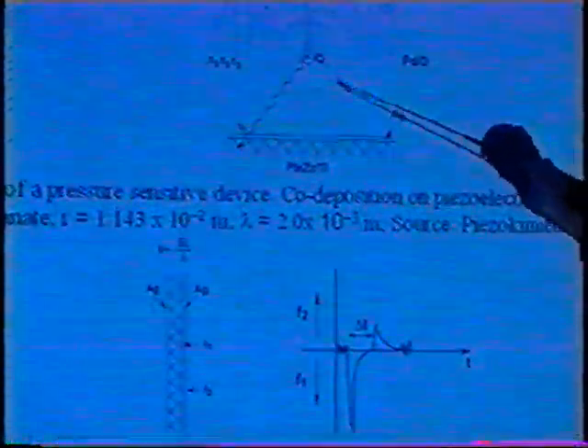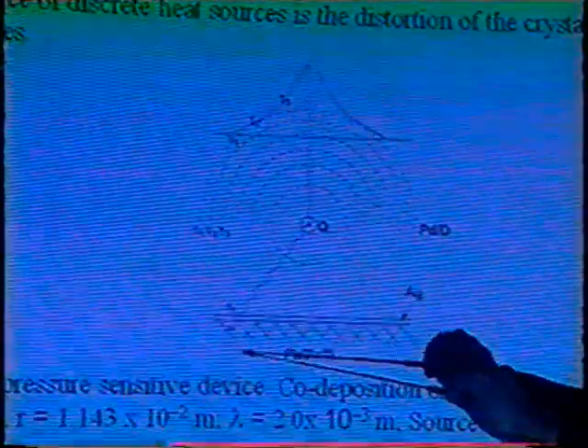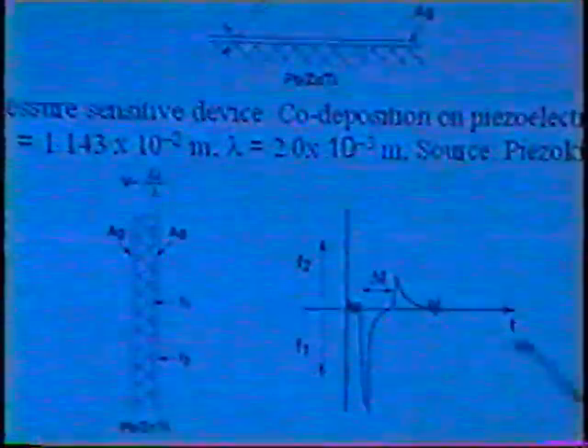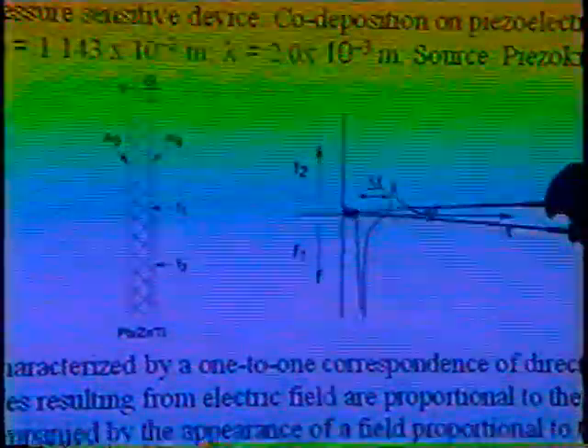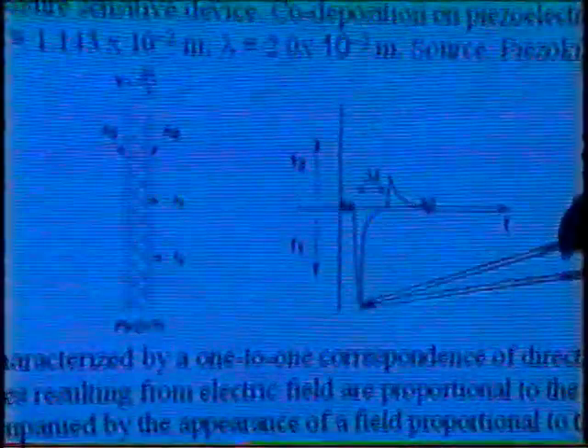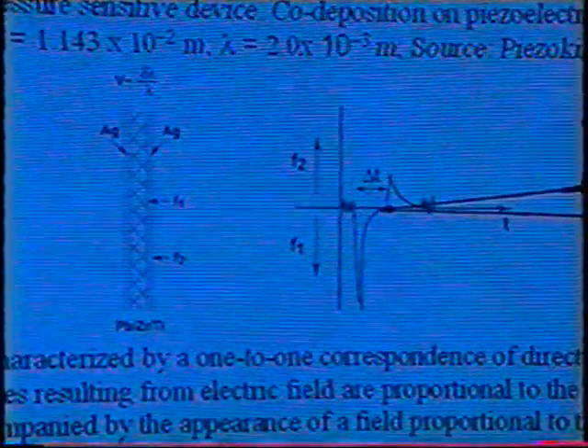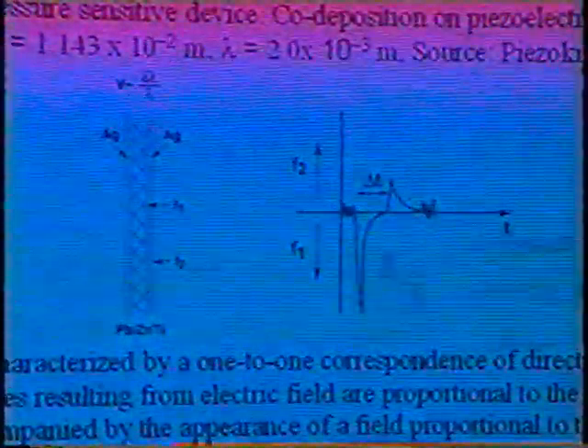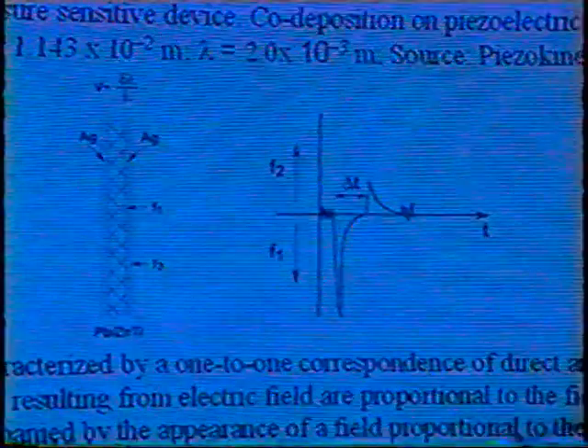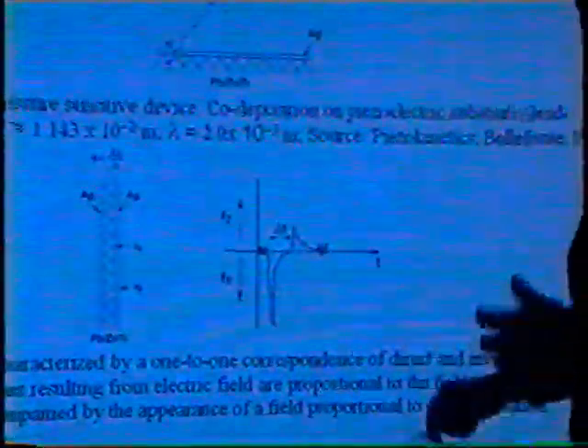The idea is that when you get a heat source, you should get a pressure wave that would hit the piezoelectric crystal, and you would see a constriction of the crystal. This would show up as a voltage response. And once the crystal relaxes and expands again, you'll see a relaxation curve. This is a very reversible system, and the areas of these curves should be approximately the same.